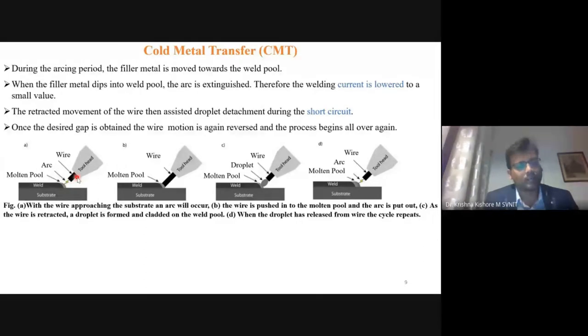Once again, after this, the electrode comes back and maintains a certain gap, and it generates the short circuit. Again the electrode heats and a droplet forms. And once the electrode is taken back, the entire droplet gets detached and is transferred. Because of switching of the current in between the transfer of the droplet, it is treated as cold metal transfer. When we check the temperature of the droplet, it is actually quite high, but compared with the MIG welding or TIG welding process, it is relatively cold. That's why the name cold metal transfer came in this fashion.